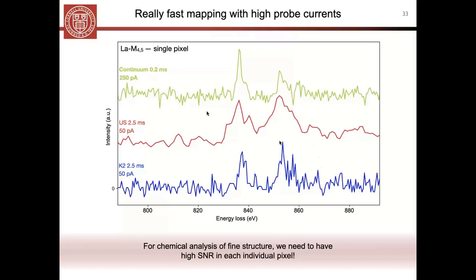And so here I'm showing you a comparison between the spectra from our Titan instrument, again, with about five times the probe current. And so you can see that even by dropping our per pixel dwell time to less than a tenth of what we were using before, because we have this huge increase in the probe current, we can really preserve that fine structure signal to noise that we're interested in for these kinds of measurements.